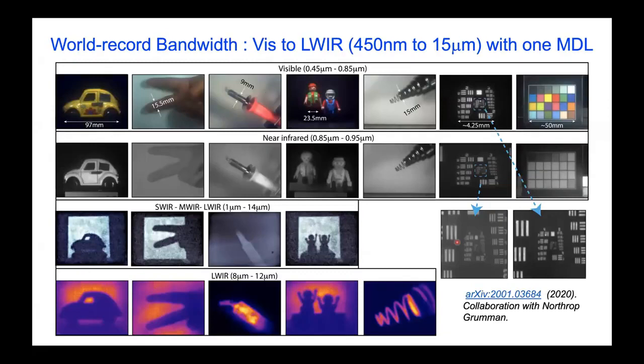What's even more striking is that this approach can be extended to pretty dramatic bandwidths as well. So this was something we demonstrated, again, a bit more than a year ago, where we showed that a single lens could actually be achromatic over a world record bandwidth from visible to long wave infrared. This is quite remarkable, because it wasn't even clear that this should be possible. And it's clearly not possible with conventional optics.